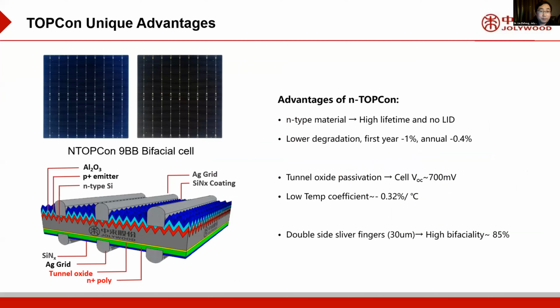And this is the TOPCon structure and picture of Jolywood. For the TOPCon solar cell, on the front side, we use the P+ emitter, boron diffusion for the P+ emitter, and deposit aluminum oxide and silicon nitride, and then print silver fingers. And on the rear side, we use 1 nanometer tunneling oxide, and then deposit N+ poly, and then deposit silicon nitride and print silver fingers.